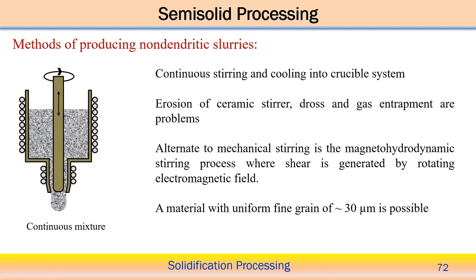Now, the techniques and methods of producing the non-dendritic slurries are very important in semi-solid processing, because with non-dendritic slurry the required shear stress is low. In this case, we try to promote the non-dendritic slurry, so we can avoid the dendritic structure.